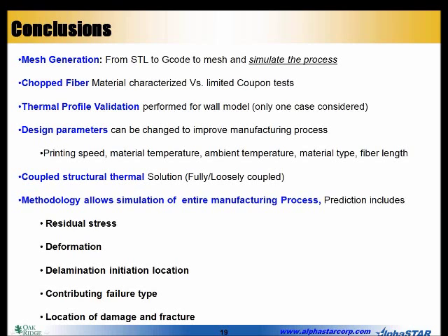The software that we have developed enables different solution types, both fully coupled as well as loosely or sequentially coupled. And the methodology finally allows the predictions of residual stresses, deformations, delamination initiation and growth, the failure type and location of those failures, and this is all basically done in an automated way to simulate the production process.